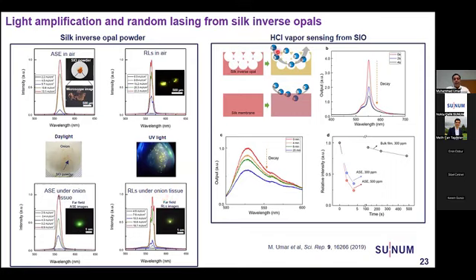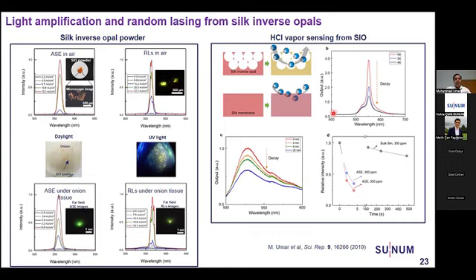Also, we utilize this because sodium fluorescein is pH sensitive. So hydrochloric acid vapor can quench the PL of the sodium fluorescein. We see the amplified spontaneous emission decays when we expose the sample to hydrochloric acid vapor for 2 seconds and 4 seconds. So the spectrum decays very fast. On the other side, the PL-based spectrum takes 20 minutes, 30 minutes to decay to the same level. So this means this kind of silk inverse opal based platform can be utilized for random lasing in biological tissues to scan or engineer them, as well as to sense hydrochloric acid vapor or some hazardous vapor.